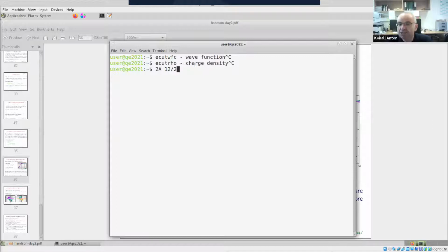So I can take 12 by 12 by 12. Now I imagine I go to a 3 by 3 by 3 supercell. A 3 times larger cell means a 3 times smaller Brillouin zone per direction. So I can go to 12 divided by 3, so 4 by 4 by 4 would be fine, right? Then I go to a 4 by 4 by 4 supercell, which means 12 divided by 4, so 3 by 3 by 3 K points would be okay.